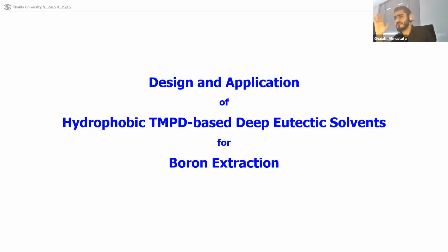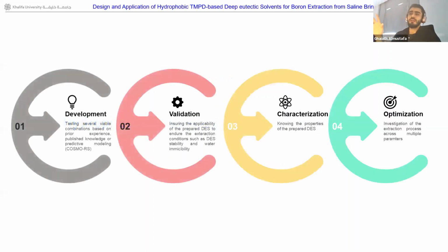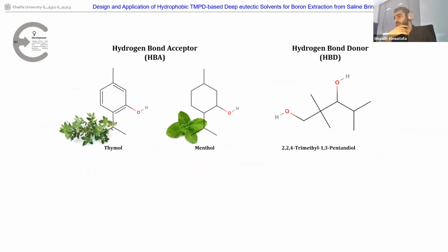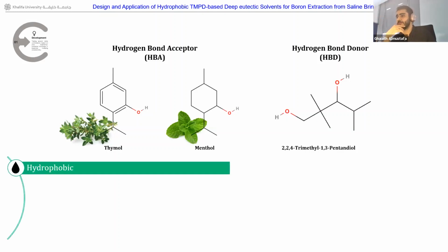I'm going to show you the framework that we discussed here for the development of these. It's basically in 4 phases: the development, validation, characterization, and optimization. For the development phase, we basically focused on the selection of the right materials to form the hydrogen bonding for the DESs, and we depended on thymol and menthol as the hydrogen bond acceptors and TMPD as the hydrogen bond donor. And that was not an arbitrary choice.